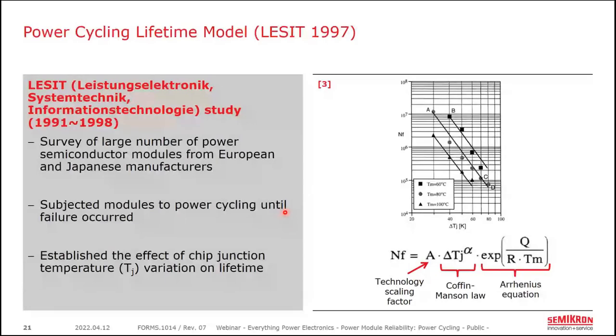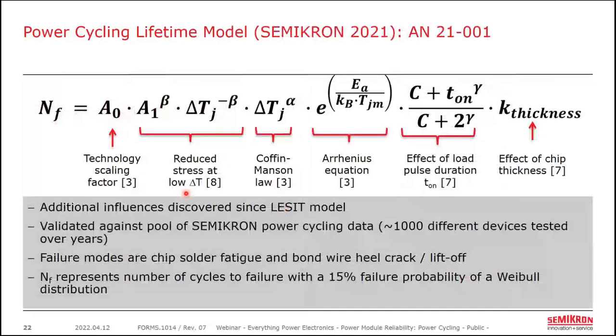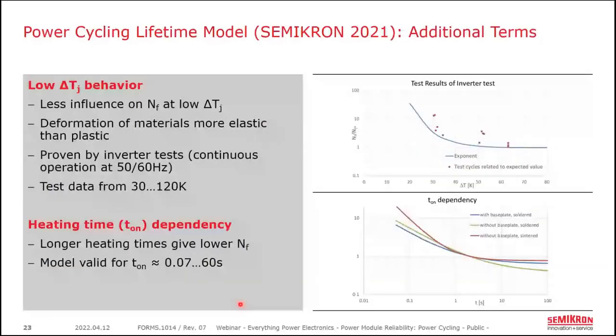This model, like I said, we've gone back and validated this against a huge amount of tests that we had. So we have all these tests that Semikron has done, and they have varying heating times and varying other parameters, and the model was adjusted to make sure it fit the data. And so we say we're relatively confident that the model we have here is accurate for heating times of approximately 70 milliseconds to 60 seconds. That doesn't mean that the model doesn't work at higher or lower heating times, but we have not been able to validate it experimentally.